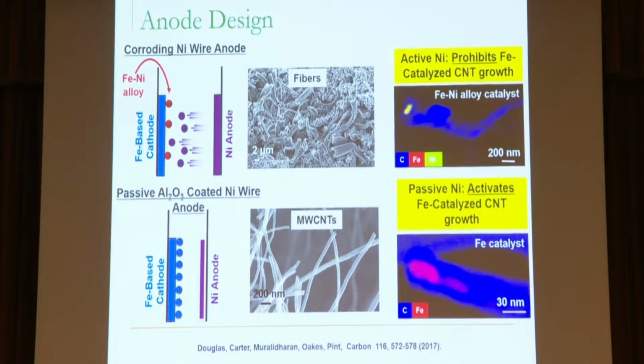Well, okay, this is electrochemistry. So what can happen is that your nickel can corrode into your electrolyte and literally go to the other side. So it poisons our whole system, right? That's not good. And so we can't grow something good with nickel. Iron is going to always be our best catalyst material. So what we did is we used a process called atomic layer deposition. Basically put a thin layer of aluminum oxide on the surface. Aluminum oxide is a stable material. And if you make it thin enough, it prevents this corrosion effect, but it still allows charge transfer back and forth in the system. And also, because that's the electrode where oxygen evolution takes place, it facilitates oxygen to evolve. It was like turning on a light switch, right? We saw these beautiful nanotubes, right?